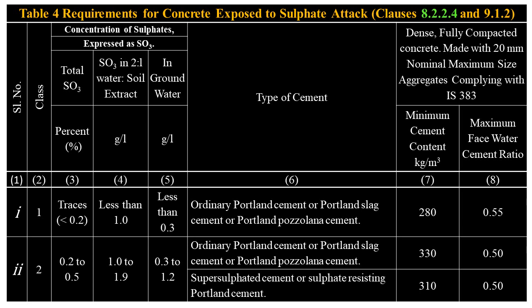Type of cements: ordinary Portland cement, or Portland slag cement, or Portland pozzolana cement. Minimum cement content, 330 kilograms per cubic meter. Maximum free water cement ratio, 0.5.